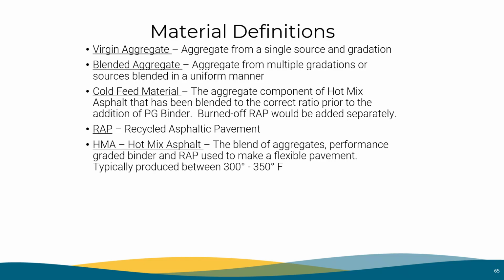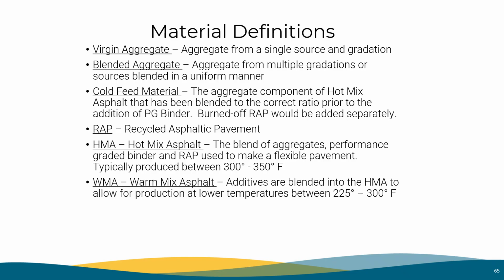HMA or hot mix asphalt is the blend of aggregates, performance graded binder, and RAP used to make a flexible pavement, typically produced between 300 to 350 degrees Fahrenheit. WMA or warm mix asphalt is when additives are blended to the HMA to allow for production at lower temperatures, between 225 degrees to 300 degrees Fahrenheit.